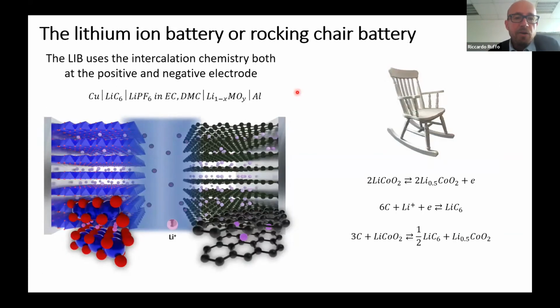So the lithium-ion battery, which is now in the market, has several advantages, but the most important one is the use of intercalation chemistry, both at the positive and negative electrodes. And this intercalation chemistry makes the lithium-ion battery a very reversible device.